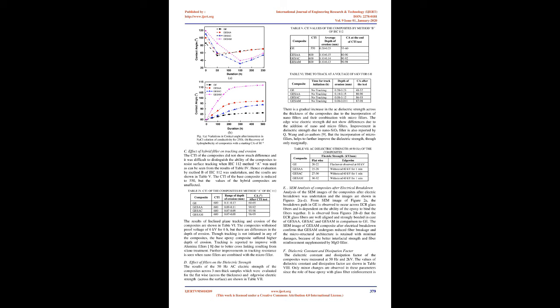The variations in Ca of composites as a function of time duration when immersed in water is shown in Fig. 1a. In all the materials, it is observed that the Ca decreases due to diffusion of water into the bulk of the composites. However, it is interesting to observe that 2 distinct minima of the Ca are seen, one at 50 H and the other at 150 H respectively.